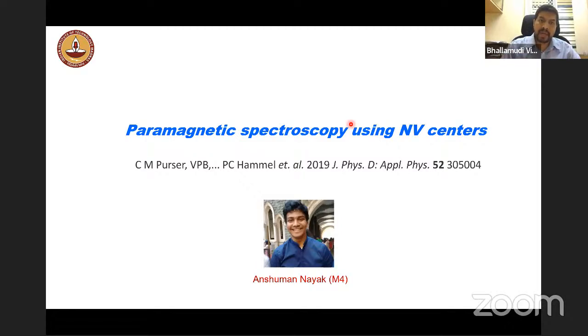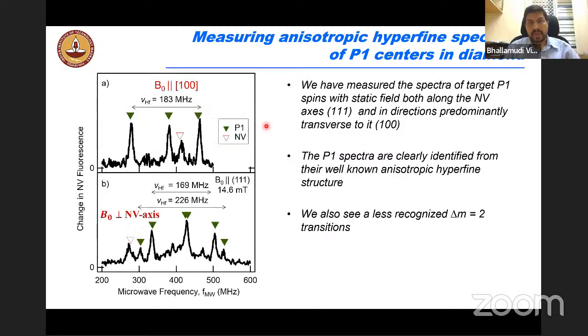The next one that I'll be looking at is paramagnetic spectroscopy using NV centers. And what we see here is again an experimental observation that these are P1 centers that we are looking at. P1 centers are substitutional nitrogen centers. So when they combine, I realized just now that I had never actually highlighted what the NV center was. I should have pointed out that the NV center is a nitrogen vacancy coupled with a substitutional nitrogen. That is what an NV center is. And I apologize for not setting this out in the beginning itself. And so the P1 center is the substitutional nitrogen center that you have. And so you can have a coupling between the NV and the P1 that you will see.